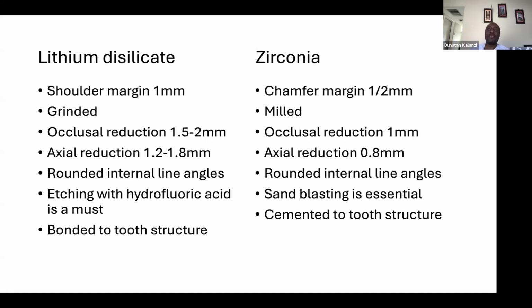So grinding is a manufacturing process. Whether it is grinding or milling depends on the material you're using and the machine doing the work. Some materials which are very strong need to be ground, because you use frictional resistance and diamond burs. Milling applies to softer materials, your polymers, your zirconia, and partially sintered materials. It uses rotary cutters. So it's a softer material to cut, and it cuts to fine detail. And then you can do the full crystallization through what? Sintering. So it's a manufacturing process.